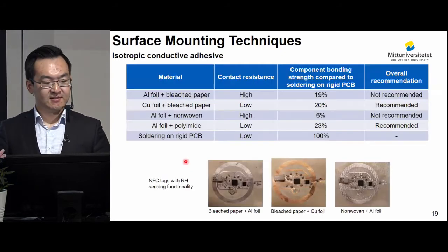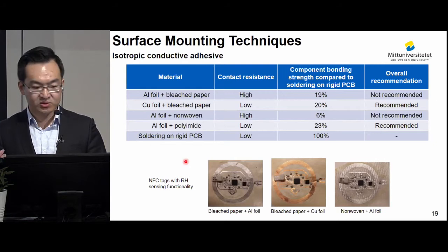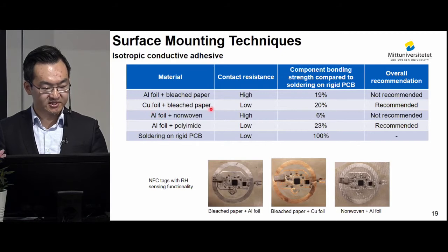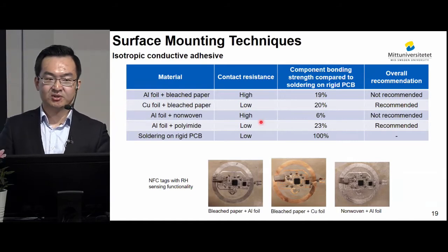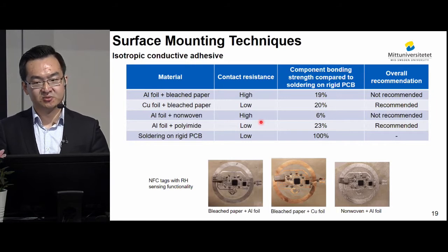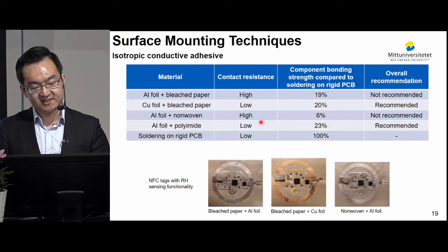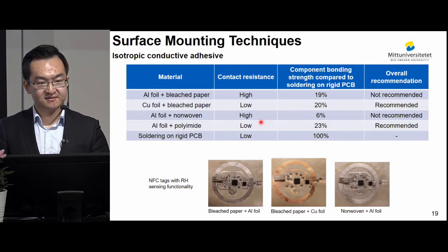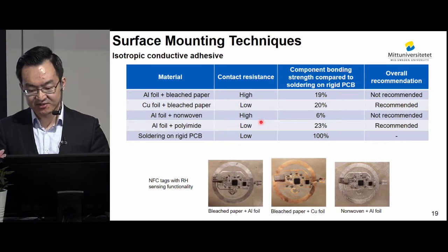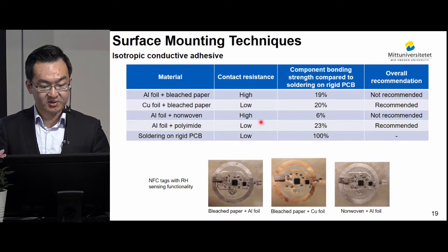The result showed that we could recommend using this surface mounting technique to mount components on copper paper circuits and aluminum polyimide circuits. The contact resistance achieved on aluminum paper and aluminum nonwoven was high. This was because during the fabrication process, a layer of adhesive remained on top of the aluminum foil, which was difficult to clean because the surface roughness of the aluminum foil we use is high. So it trapped a lot of adhesive, which means the surface of this aluminum foil cannot contribute as many electrical contact points as copper. So that's why it's not recommended to mount components using this technique on aluminum paper and aluminum nonwoven circuits.